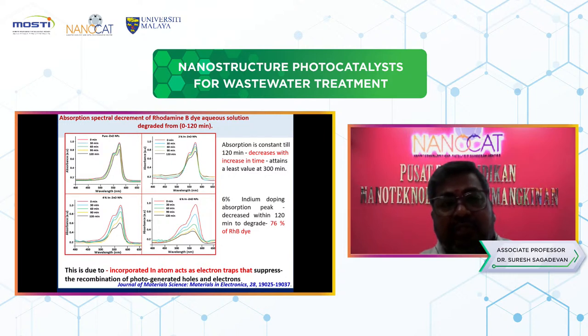You can look here, this is the UV absorption spectrum, and how it decreases with respect to time. The first figure represents pure zinc oxide, and the second, third, and fourth figures represent 2%, 3%, and 4% indium doped zinc oxide nanoparticles, and then 6% indium doped. You can look here at the decrease of intensity peaks for 120 minutes at the higher doping concentration, which means that 6% indium doped zinc oxide has a maximum of dye degraded, 76% of the rhodamine dye.